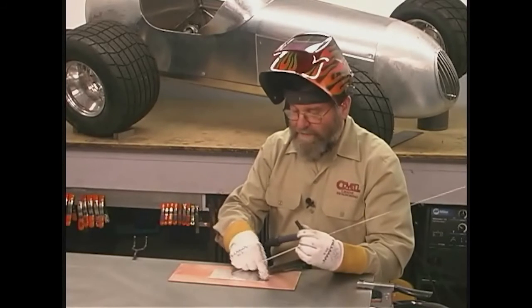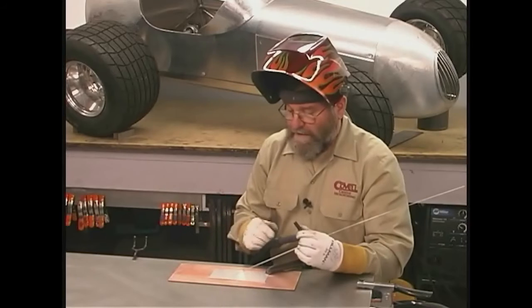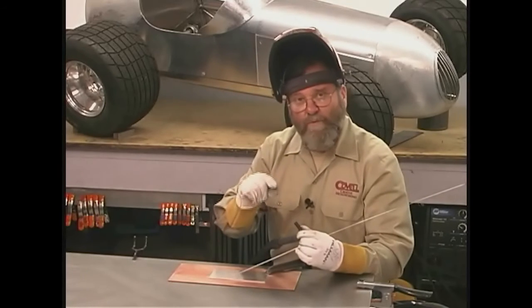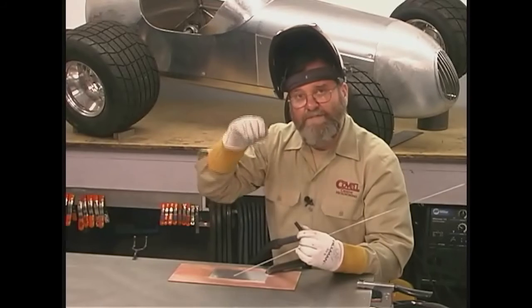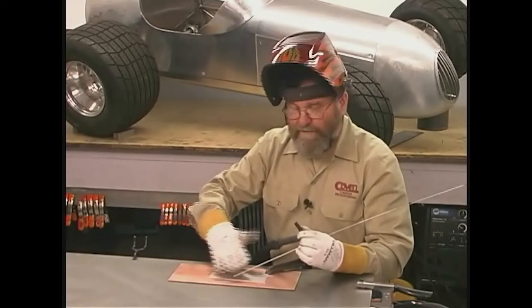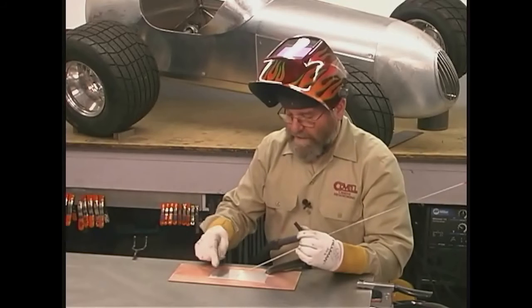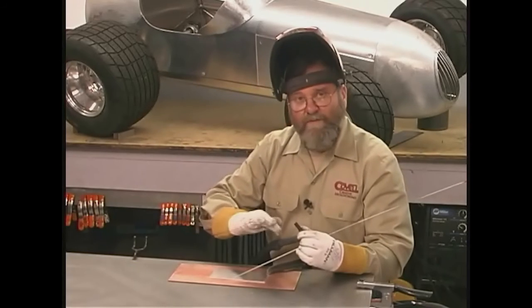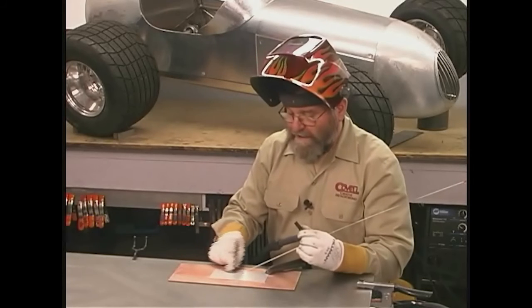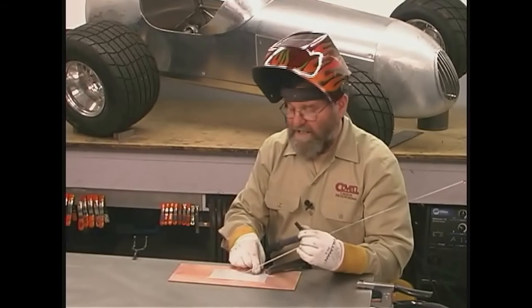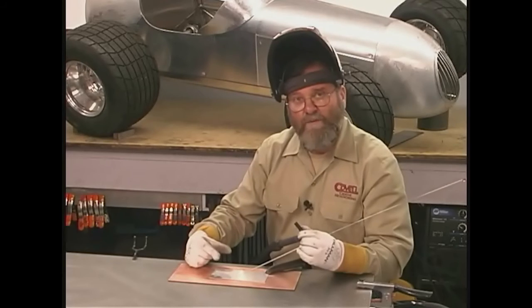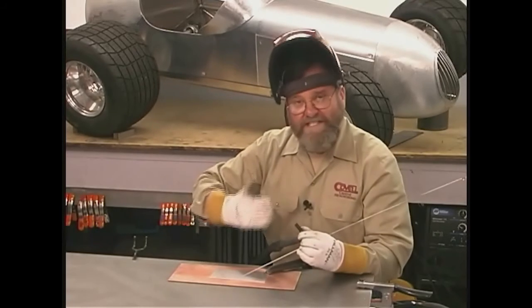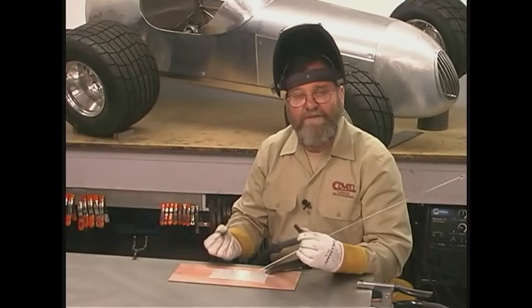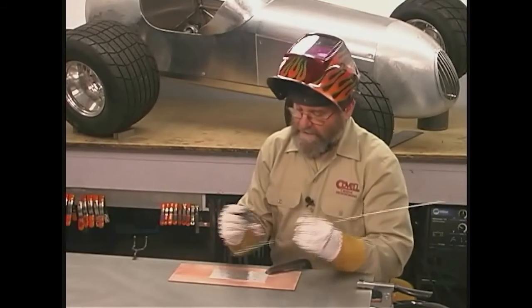I'm going to run 3 beads on this piece of aluminum plate. I'm going to make the first bead with not enough heat. What you'll see is kind of a wormy little weld bead that stands up tall above the surface and doesn't flow into the base metal very well. The next weld will be nicely rounded, and you'll see that it does flow in nicely to the plate around it. And the last weld will be made with way too much heat. You'll see that the weld bead is very wide, and I'm probably going to get more sagging of the weld, so it's going to bleed through the backside a lot. Here we go.